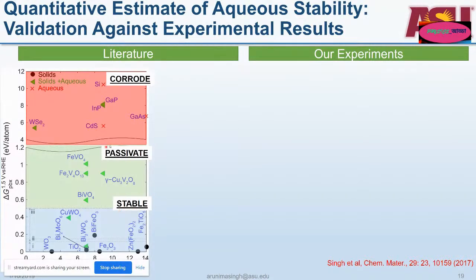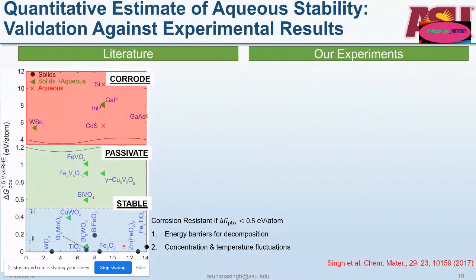The materials which were above that value, up to about 1.2 electron volts per atom, were reported to form passivation films, which would be a few nanometers thick and would prevent further corrosion. Materials which had very high delta G values were reported to corrode. And it's surprising that with delta G values of up to 0.5 eV per atom, even though your materials are unstable by that amount, they were still not dissociating to Pourbaix stable phases, and